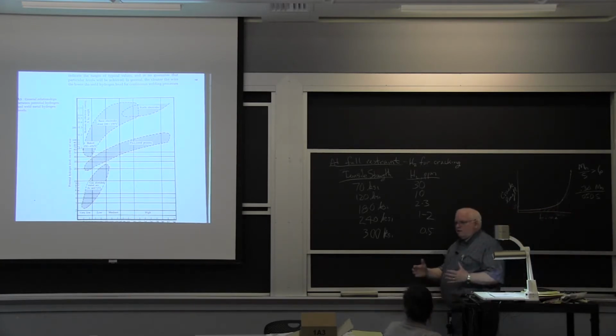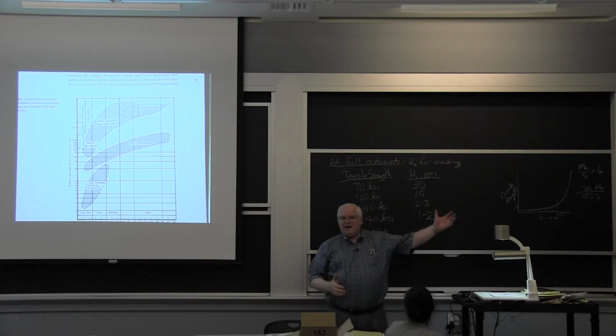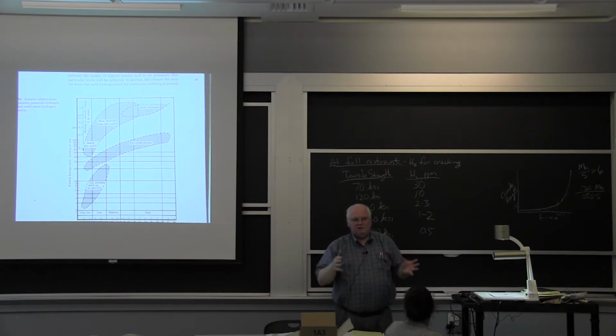They'd done all kinds of hydrogen tests, and I plotted this, and I found the highest hydrogen in the welds, or the wires. They actually measured on the wires. They tested the wires for hydrogen because there'll be some residual hydrogen. This was highest. This was next highest, and this was the least hydrogen. And so, what was the conclusion? That's the data I had. And there was a range. These ranges actually overlapped if you looked at all the individual measurements they had made.